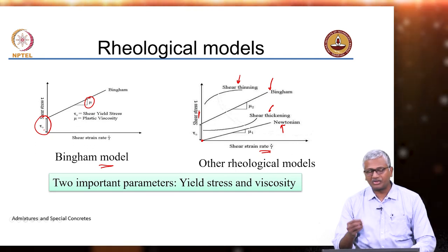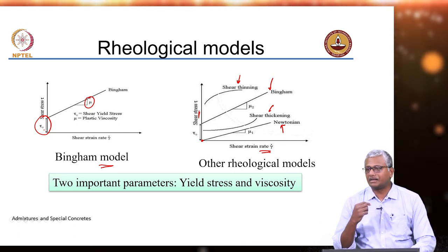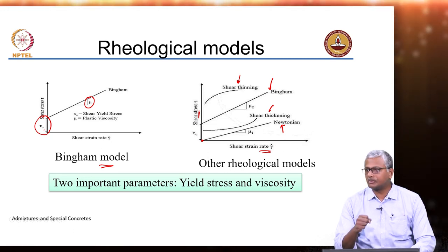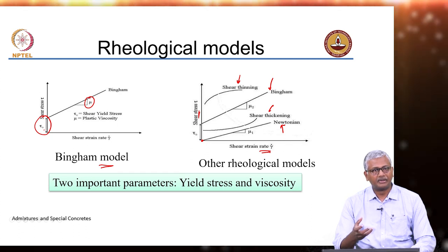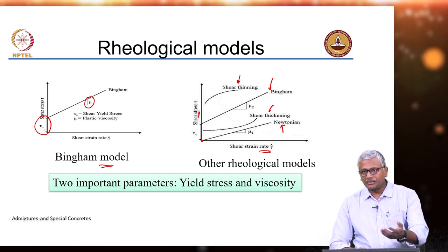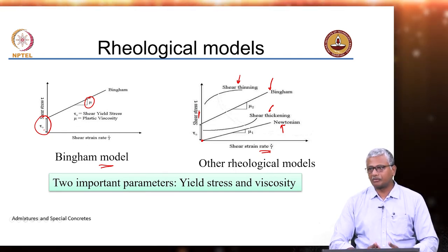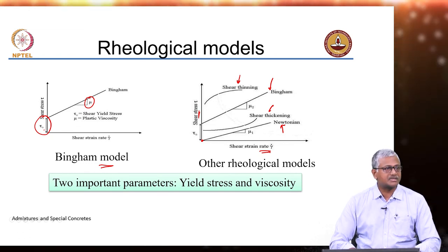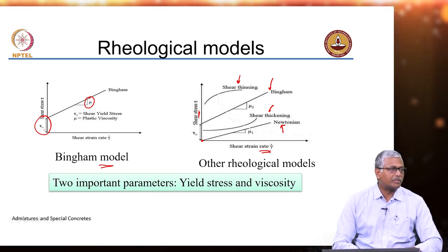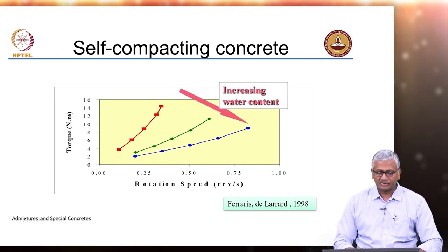In most cases when we talk about concrete, we would like to get a shear thinning behavior so that concrete at high shear rates is able to flow fairly easily with a low viscosity. But when it comes to rest, it builds up the internal viscosity, and that build-up is related to what we call the thixotropic property of the concrete. The viscosity modifying agent actually causes the concrete to exhibit thixotropy — so the thixotropic property is essentially introduced by the viscosity modifying agent.